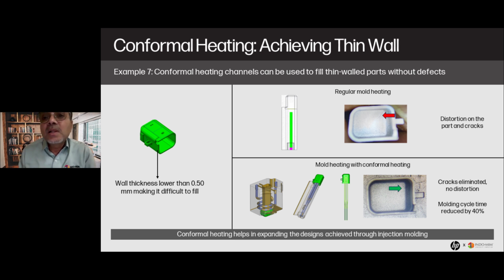So in the conventional design, we only had a straight line, and we really struggled with filling this component. But then when we redesigned the part with a conformal, I'd like to say heating, we were able to pass the heating liquid into the cavity and keep the mold at a required uniform temperature, so that we were able to fill very effortlessly. And because of that, the cracks and other issues that we used to see in the component completely vanished when we actually used the conformally heated inserts.